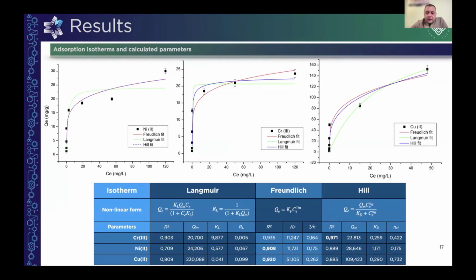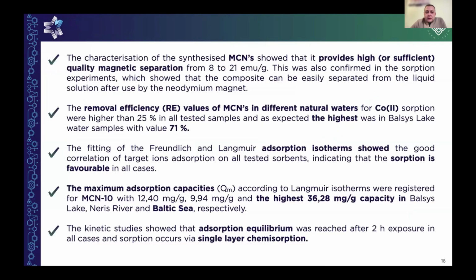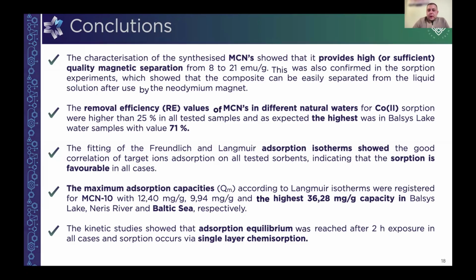So we tried to use the most magnetic sorbent, which is easiest to separate from the samples and to test. Here are the results, and here are some conclusions that we can say about our magnetic chitosan: it provides sufficient quality magnetic separation. It also removes cobalt from natural waters with higher than 25% removal efficiency, and the highest was 71%, as I told you before. Furthermore, isotherm studies show that it's favorable sorption. Maximum sorption capacities are also mentioned, and the highest was 36, and the equilibrium and kinetic studies show that it's single layer chemisorption. So thank you for your attention.